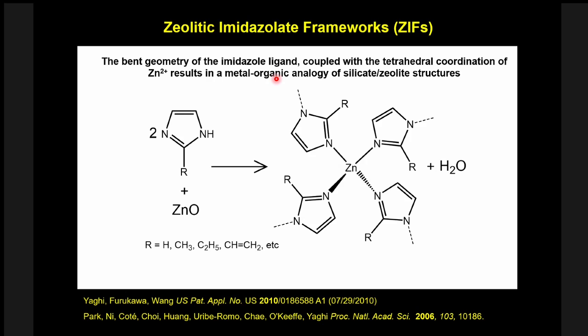We developed a really, really simple process to make these zeolitic imidazolate frameworks, ZIFs, which essentially mimic the structure of zeolites, which have a tetrahedral silicon or aluminum bridged by oxygen. They mimic this structure by taking a tetrahedral metal like zinc or copper or cobalt and so on. And instead of oxygen atoms to bridge them, they use these bigger organic ligands, imidazolates. So this is one very, very popular and very well-known family of MOFs, and we wanted to know how we can make them from a metal oxide, and the solution was extremely simple.